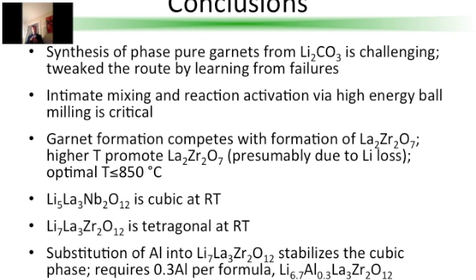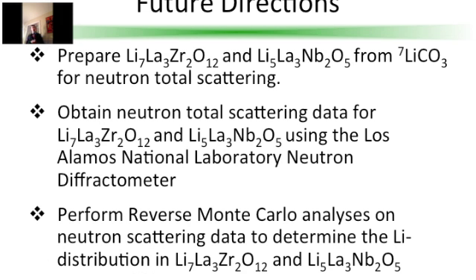Now, I still see that a small fraction of other phases exist in my lithium lanthanum zirconate samples, so I still need to fine-tune the route to get the phase pure garnets. Currently, I'm working on this to prepare phase pure lithium lanthanum zirconate for neutron total scattering. As you recall, earlier I mentioned that I had difficulty removing the trace amounts of lanthanum zirconate oxide from the sample, so I still need to tweak the conditions a bit more.